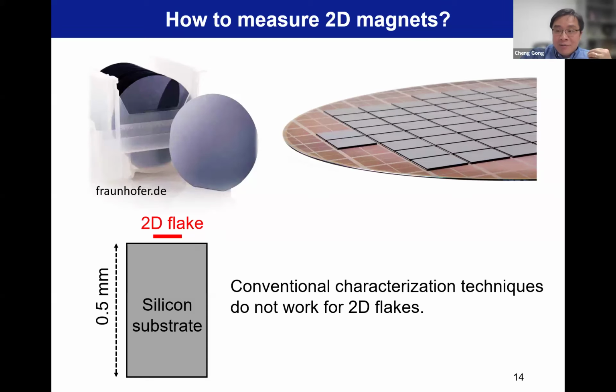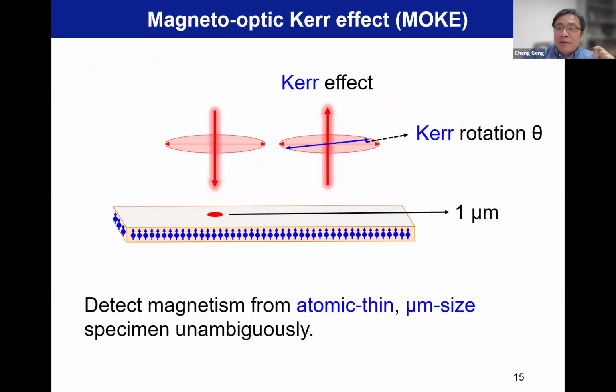So if you put such a chip in the VSM for magnetic hysteresis loop measurement, even though you see some tiny hysteresis loop window opening, it's very hard to believe the signal is really just from this flake rather than from other flakes, other edges, or even the substrate and or interface. So we need some area selective method. It's better to be surface sensitive to just pick up the signal from that flake.